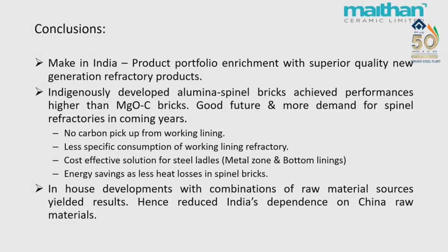So finally the conclusion is, in the Make in India drive, to enrich the product portfolio of the Indian refractory industry, spinel is the new generation refractory which is coming in. Indigenously developed alumina spinel bricks achieved the highest performance compared to magnesia carbon. Good future and more demand for spinel refractories because of the changes in steel quality requirements. That is no carbon pickup, less specific consumption, cost-effective solutions and energy saving. So in-house developments with a combination of raw material sources yielded the results, hence reducing India's dependence on Chinese magnesia materials. Thank you.